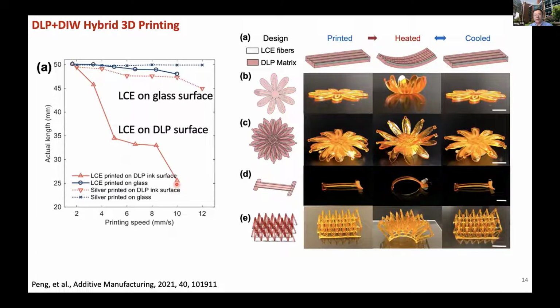Because you lose that length, the LCE printed at this stage would not give you much actuation, because all the aligned mesogens just recover back into the isotropic state. So in our case, we try to print LCE at relatively low speed, so we can make sure the LCE stays on the substrate. By doing that, we can create many different kinds of structures.